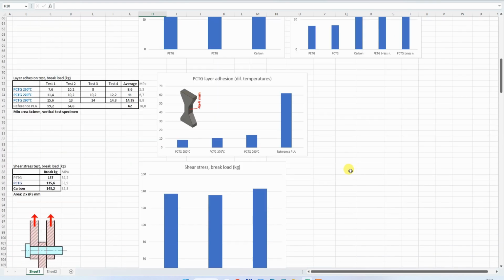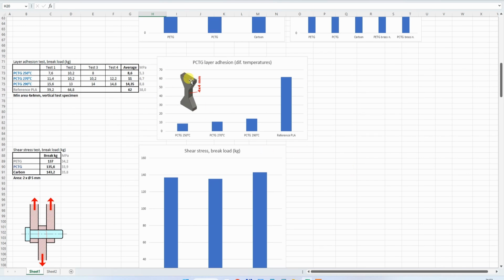And for curiosity, I printed these test objects in vertical position, 4 at a time on that Sovol SV06 Plus. And here I got even weaker layer adhesion. I'm not sure, maybe because it was printed faster or 4 at once or something like that. But this is the first time I'm using this kind of test objects. The cross-section area is the same, 4 by 4 millimeters. So for testing, I printed this reference PLA, and as you can see, it broke very similar to that break which I already tested earlier.